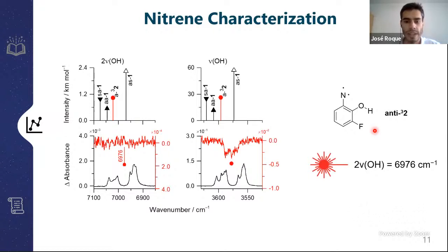Of course, we then had to proceed with a more detailed characterization of this species, because we were later intending to excite its first OH stretching overtone. So we observed that in the fundamental transition of the OH stretching, there was a broad band between the two bands of the azide. And even though we could not detect the first OH stretching overtone, based on some anharmonic calculations and on the fundamental transition, we inferred that there should be a band between the two bands of the azide and centered more or less around 6976 centimeters^-1.